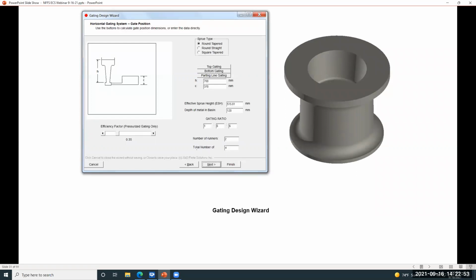Going further into the gating design wizard, we can make choices of, do we want to have top gating, bottom gating, or parting line gating? And when we make changes to that by clicking on these buttons, the schematic will change, and then we can enter pattern dimension information. We can have a choice of a round or a square sprue, and either straight or tapered. And the system will calculate what's known as the effective sprue height.